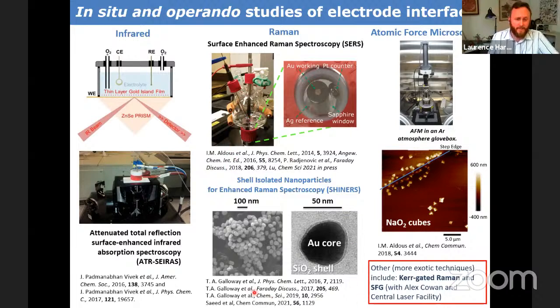As I'll explain in a bit more detail, SERS does have limitations. You're especially limited to gold interfaces and maybe just a few other materials. So what we've been using is a technique called shell isolated nanoparticles for enhanced Raman spectroscopy, which has the acronym SHINERS. We have a nanoparticle of gold, about 50 nanometers, but we put a uniform silica shell completely around it. We encapsulate it in a very thin silica shell, and it still has a plasmon resonance, and we can put these particles down on any electrode surface.